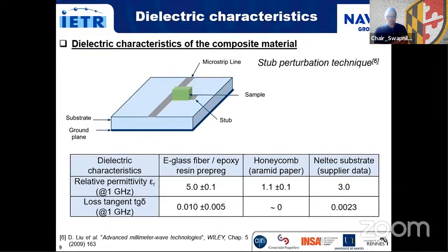The dielectric characteristics, namely the relative permittivity and the loss tangent of the e-glass fiber epoxy resin prepreg and of the honeycomb, were measured by the stub perturbation technique at 1 GHz. Those of the Neltec substrate were provided by the supplier, also at 1 GHz. As expected, the dielectric characteristics of the honeycomb are very close to those of the air.